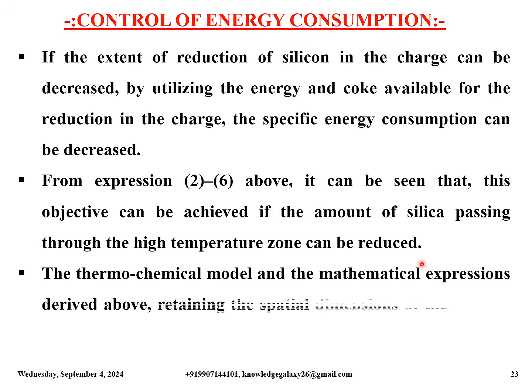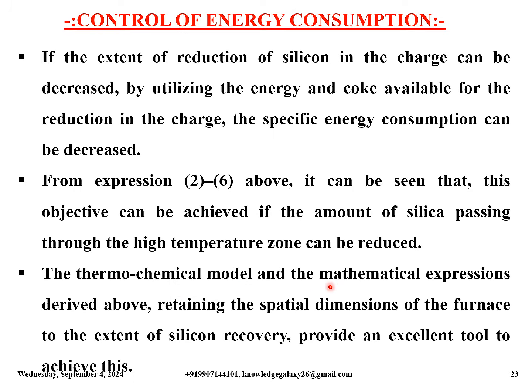From expressions 2 to 6 above, it can be seen that this objective can be achieved if the amount of silica passing through the high temperature zone can be reduced. The thermochemical model and the mathematical expressions derived above, retaining the spatial dimensions of the furnace to the extent of silicon recovery, provide an excellent tool to achieve this.